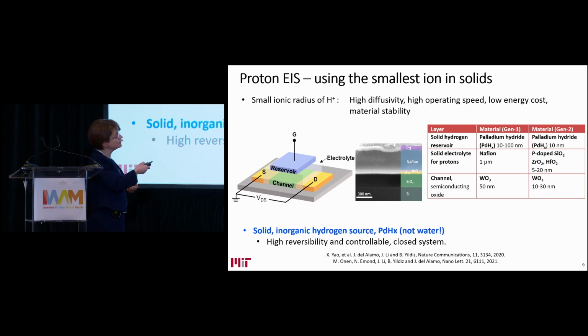And the challenge is the proton-conducting electrolyte. The best proton-conducting electrolyte at room temperature is a polymer called Nafion, and that was our first demonstration system. But when we attempted to downscale these devices, Nafion is not conducive to it using conventional CMOS nanofabrication approaches, so we had to move into insulating oxides like dielectric hafnia, zirconia, and silica, which are conventionally not proton conductors in their lattice, but I will show you how we make them just enough proton conductor.